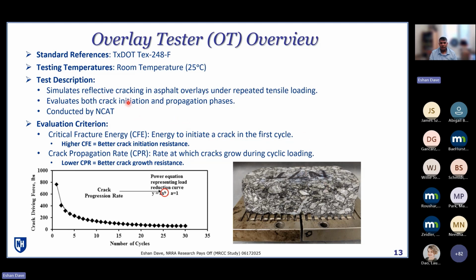So it's really a simulative test to look at reflective cracking, and there are typically two phases within this test. You initially see a phase where there's a quick drop in how much force is needed, and that's your crack initiation phase, and then there's a growth phase where that crack continues to grow with time. And so there are parameters like CFE and CPR. CFE is indicative of what kind of energy it would take to get that initial cracking to happen. CPR is simply looking at how much more that crack would grow with each repeated cycle. So there are again index parameters that we can extract out of this test.